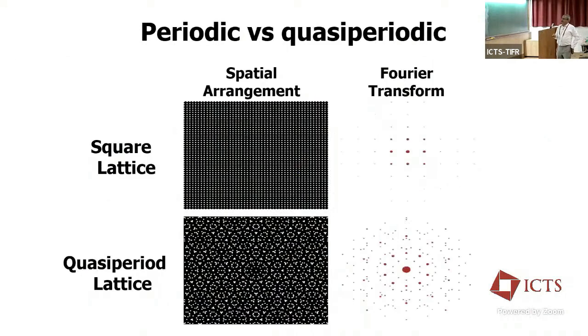Right. So there is another way of getting a broadband response, which is by going to a quasi-periodic or random distribution. Random distribution is not a unique solution, and repeatability is an issue. So we looked for a quasi-periodic lattice. This is a 5-fold rotation symmetry. If you take a certain number of scattering elements and put them in a square lattice, you see the Fourier transform, or the K-space, has discrete resonances.